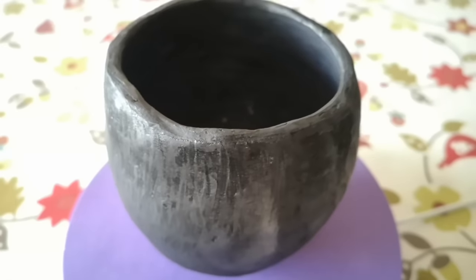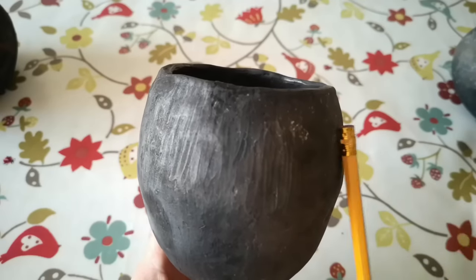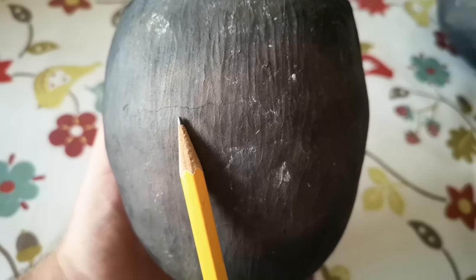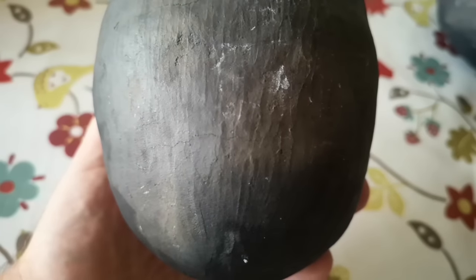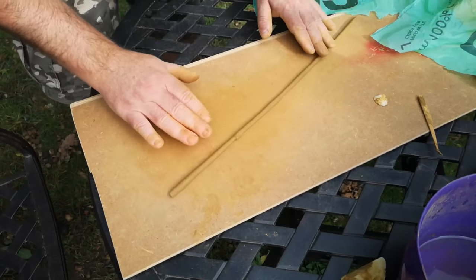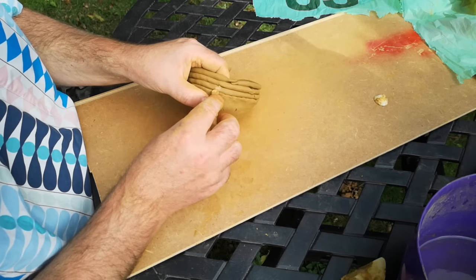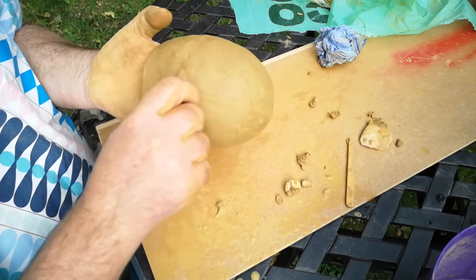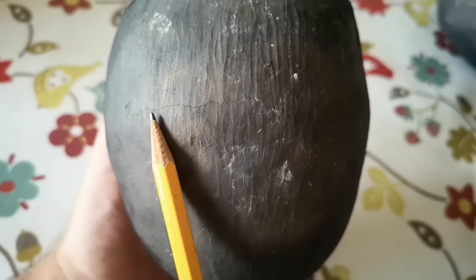This egg-shaped pot was made from just refined wild clay with no grog or temper. It seemed like the strongest and most solid of the bunch, but on close inspection I can see some thin horizontal cracks on the outside about one third and two thirds of the way up. The cracks don't penetrate all the way to the inside so it's probably okay, but I think I will not tempt fate by heating it again. A horizontal crack like this on a coil-built pot almost certainly indicates a failure to properly bond one of the coils onto the layer below — hardly surprising in a pot built from more than a dozen successive layers. The optimist in me would say the significant majority of my coils were bonded perfectly, so I'll just take a little lesson for future pots.